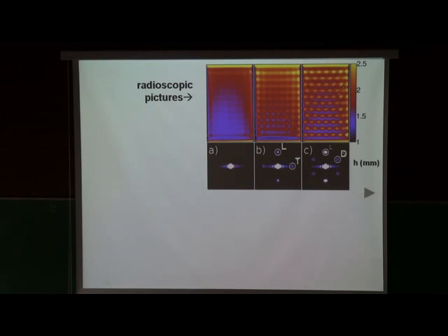Well, this hexagonal pattern can be understood, because then you are driving so fast that this liquid doesn't see these modulations anymore, and it cannot follow these fast modulations, and it just feels the average magnetic induction, and then it does its standard hexagonal pattern. But the intermediate regime is interesting, that you get a kind of square pattern, which you never have in a regime with constant magnetic inductions.